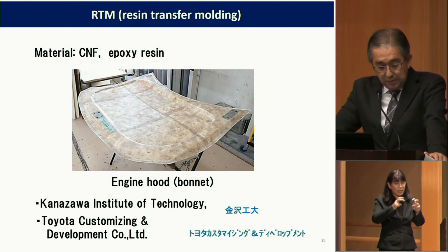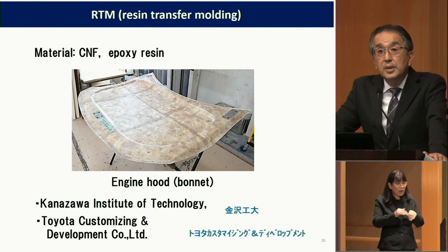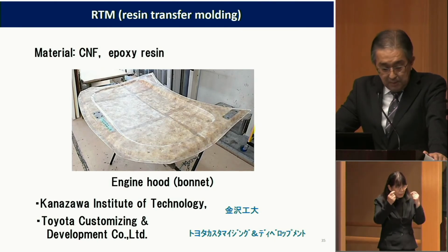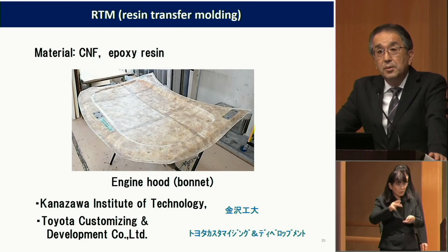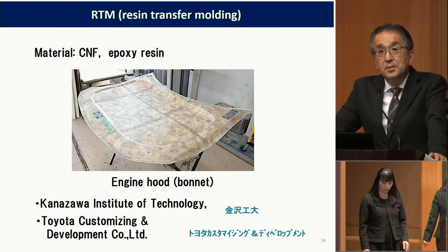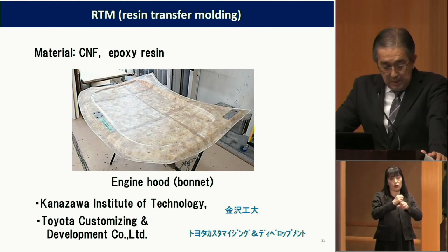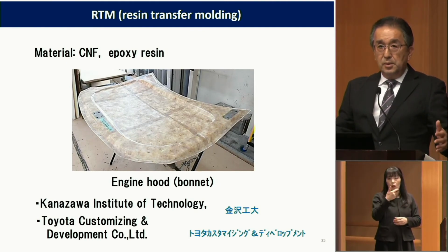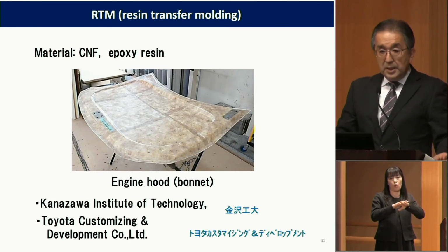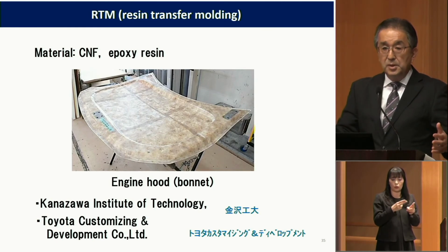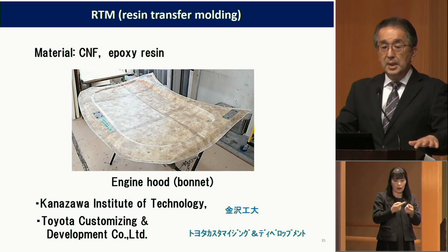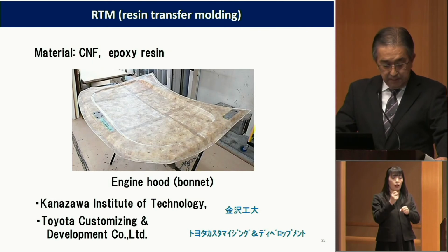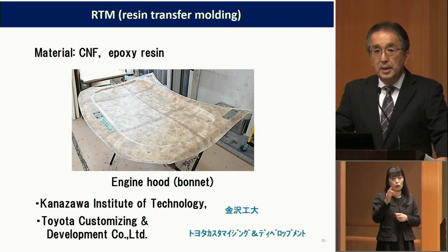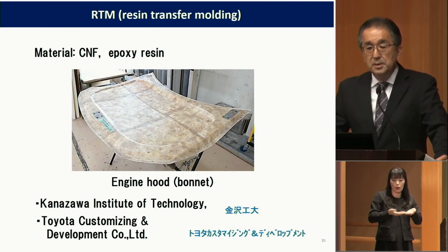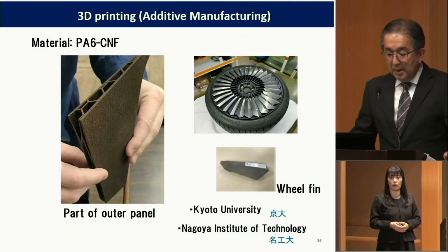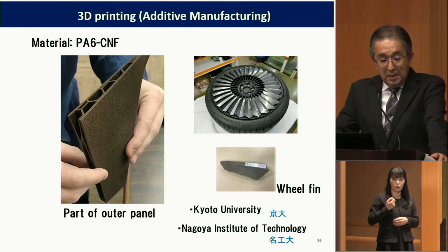This sample was prepared to replace the engine hood of the existing vehicle Toyota 86 by Kanazawa Institute of Technology and Toyota Customizing and Development. So again, a special method was used for that, which is RTM, resin transfer molding. So this is often used for large molding parts, using CNF sheets. The CNF was impregnated with epoxy resin and low pressure was applied. So of course, this prototype is lighter than conventional metal parts. This is very interesting again.